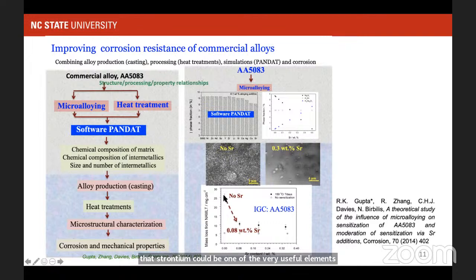So here is an example without any strontium. You see the weight loss is like 25 milligram per centimeter square. As we add a very small amount of strontium, 0.08 weight percent, you see those values on the y-axis decrease quite a lot. That shows how we could improve the corrosion resistance, and these thermodynamic calculations combined with our knowledge-based alloy design become a powerful tool in designing new materials.